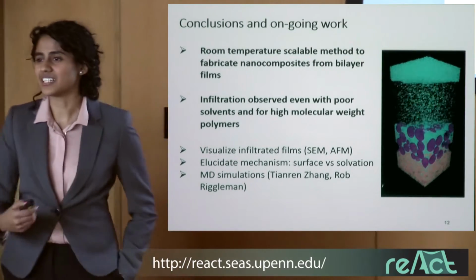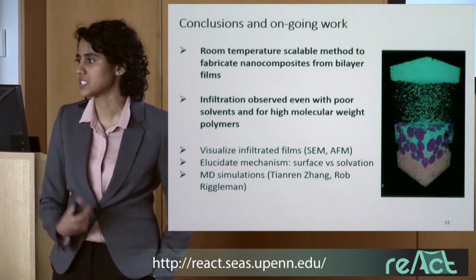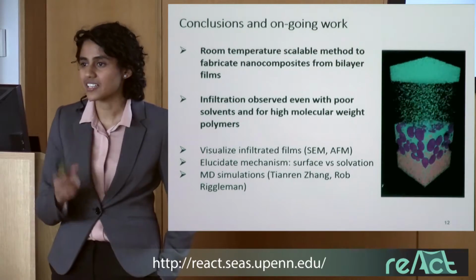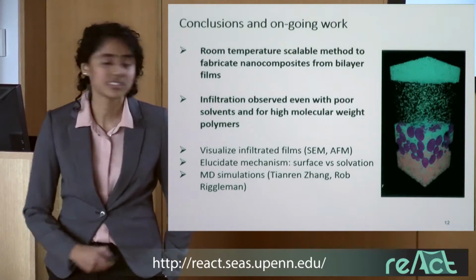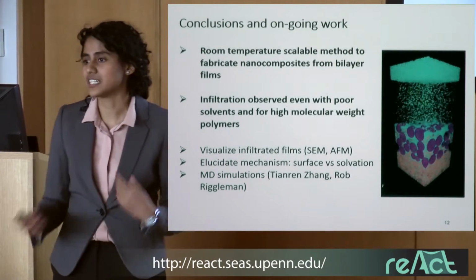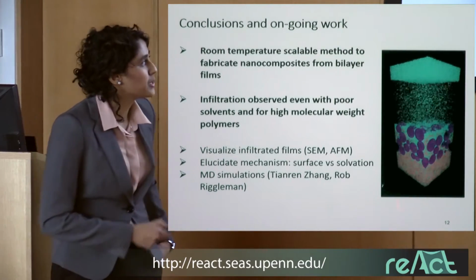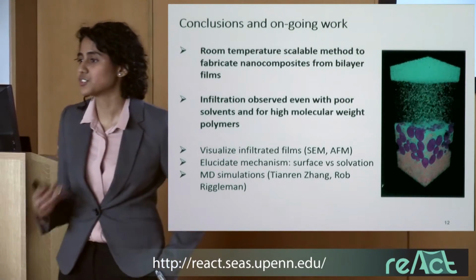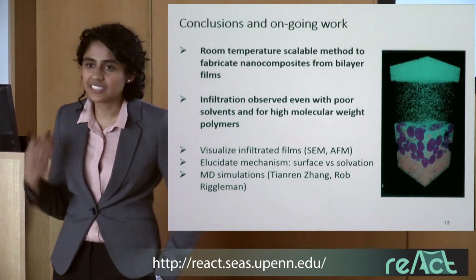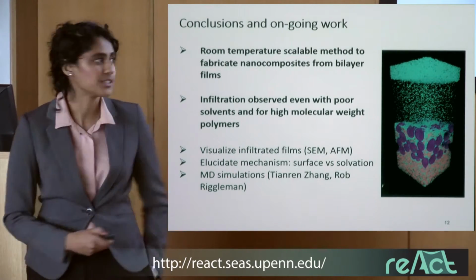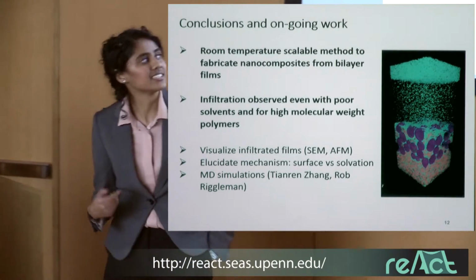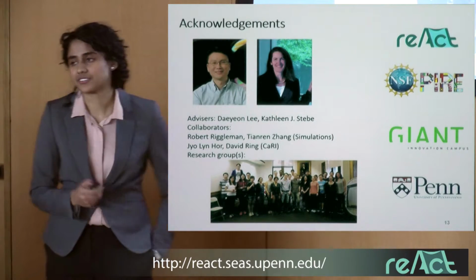And this is very exciting because we can tune the interactions between our different species and see if it's entirely surface mediated or if it's more driven by solvation, and see how the dynamics look for those cases. And we also want to visualize our infiltrated films better and maybe see if they're more mechanically reinforced and do other testing to understand the dynamics of the system.